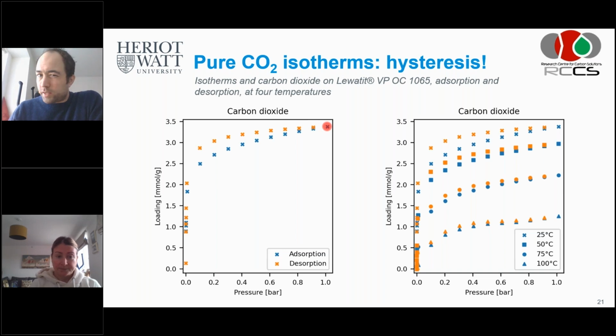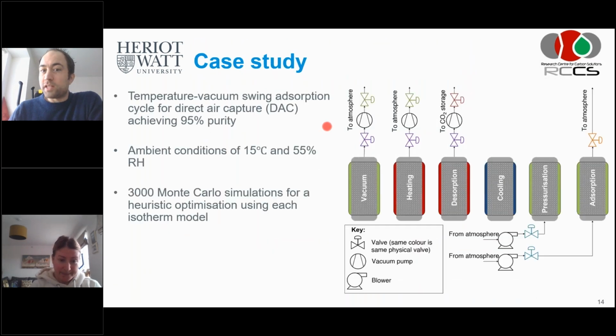I don't know if my screen is still sharing, is it? It is, yeah. Okay, that's basically why we do this 5-step cycle, because we evacuate first, before we start heating, all the nitrogen and oxygen from the bed. So that removes the oxygen as much as we can. Then we start heating and remove a little bit more, because as you start heating, some of the water starts to desorb. So more oxygen is thereby also released from the pores and from the bed voids. And only then we move to the full regeneration temperature of the sorbent. So you can engineer that degradation effect out, and it actually works quite well.